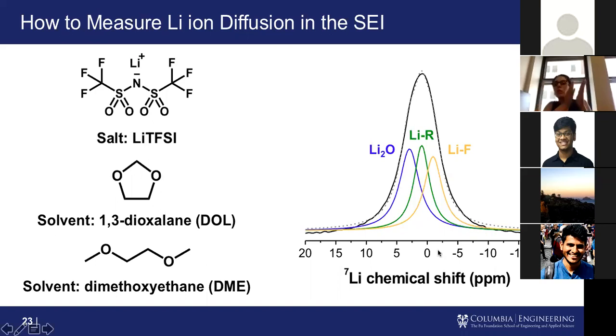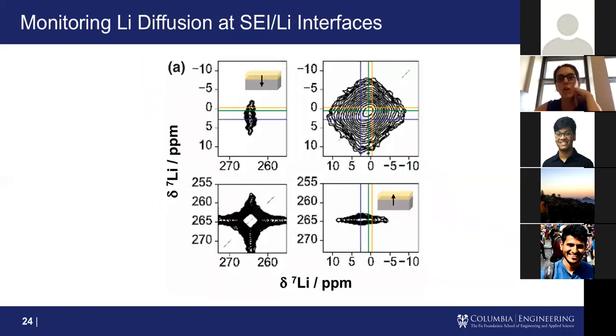So you can see that all of these different regions of this bulk lithium envelope correspond to different lithium species. And we can see how lithium ions diffuse in lithium oxide, organic lithium compounds, and lithium fluoride to see where the bottleneck is in the SEI. The way that we do that is we use an experiment called EXSY. It stands for exchange spectroscopy.